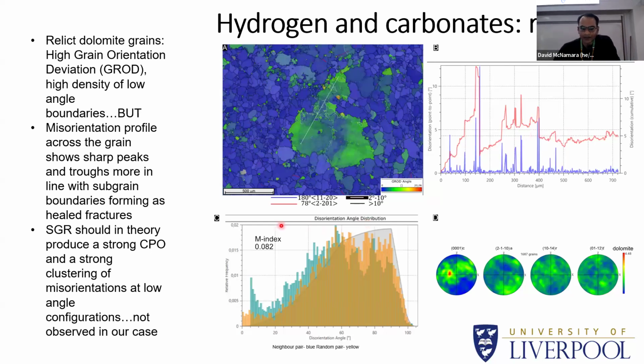Additionally, we also calculated the M index for these domains. The M index is a parameter that you can use to quantify fabric strength in your rocks. It varies between 0 and 1. So 1 is like a single crystal direction, so it's infinitely strong, and 0 means that it's completely random. You have no preferred orientation. So in this domain, we have an M index of 0.082, which is really low. So there's no preferred orientation. And if we recrystallize the dolomite by forming subgrains and then rotating them into newer orientations, we would expect a slightly stronger fabric than this. So it's possible that the finer grained dolomite that we see here is just formed by the fracturing and cataclasis of coarser grained dolomite grains.